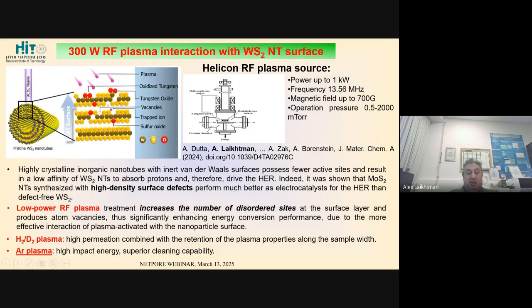So we suggested that this low power RF plasma treatment increases the number of disordered sites at the surface, and we will prove this experimentally, and produces atom vacancies, significantly enhancing energy conversion performance due to the more effective interaction of plasma-activated sites with the nanoparticle surface. So why do we use these two types of plasma? Sometimes just one type of plasma, and sometimes one after another, but never simultaneously.